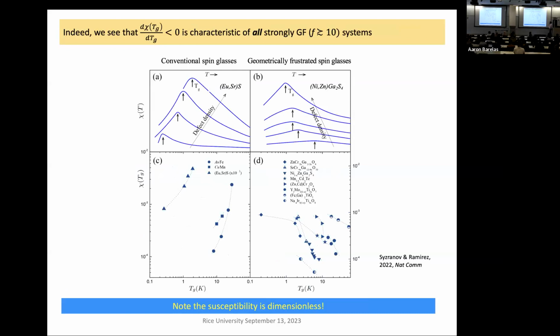If anyone can find more systems that I can put on the slide, I would appreciate it. But this is all the data I could find where systematic studies of the susceptibility with the concentration of magnetic ions were done. All of the conventional spin glasses show this behavior, which is the intuitive behavior. All of the geometrically frustrated systems show the opposite behavior. Stare at this for a while. I should make this animated, but you can see it's all the same. Here the susceptibility is dimensionless.